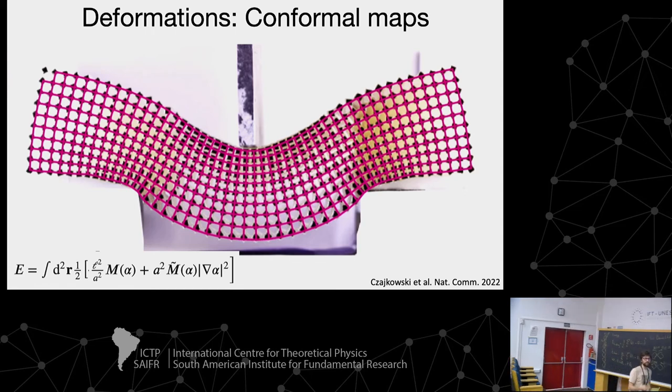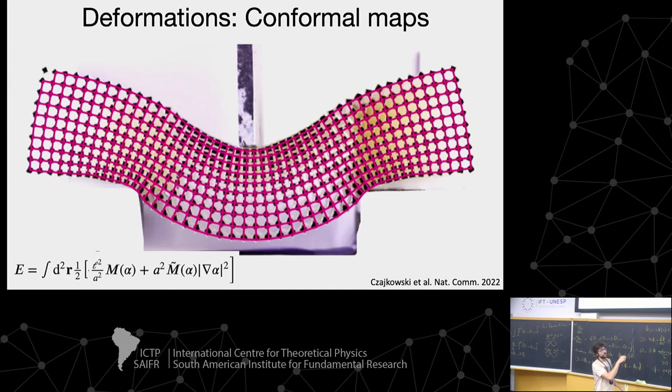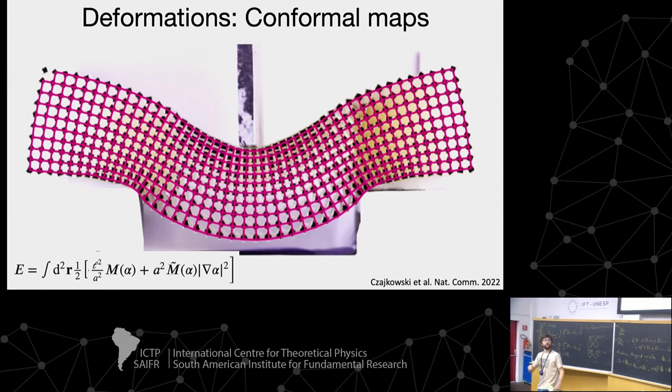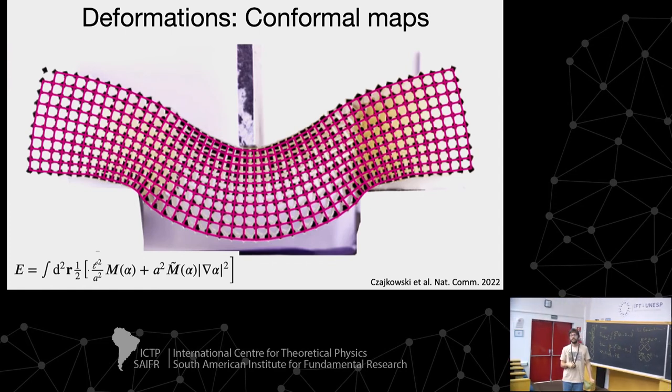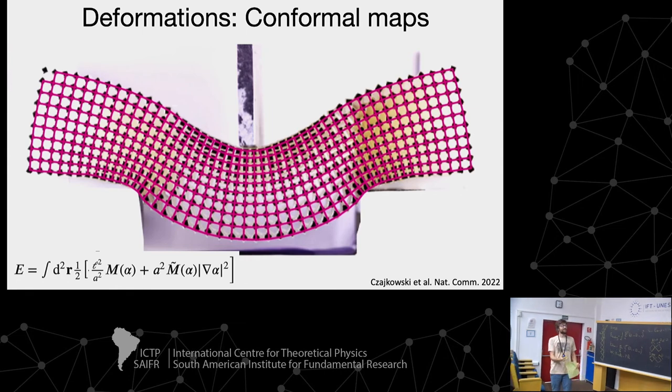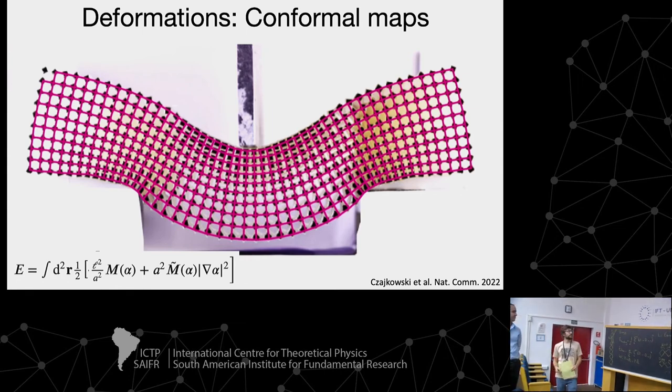Okay? But the physics is the same. The physics is, it will cost you a lot to actually do this. This kind of loading condition, like three-point bending, is incompatible with pure homogeneous deformation, so you will have to have gradients of dilations, right? And so the idea is that whenever you do something real, what's beyond the mechanism is actually to describe these distortions or deviations from the pure mechanism. And there's more than one way of doing it. This is one way that's perhaps quite promising because you can push it into the nonlinear regime, since you can construct a scalar field theory for elasticity.